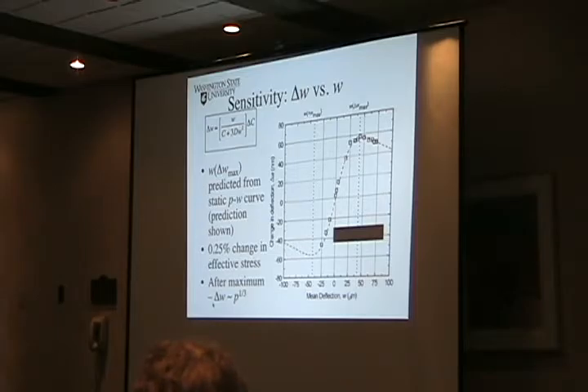If you did interdigitated electrodes to take advantage of 3-3 kind of modes, you do get different sensitivities, but they actually end up scaling the same way for membranes. For cantilevers, you have to worry about the neutral axis, and if you had a thick piezoelectric film and you don't make a bimorph, so you don't pull the compressive side and the tensile side opposite, then it doesn't work. So these are all 3-1 mode, and we're going to go to large strains.